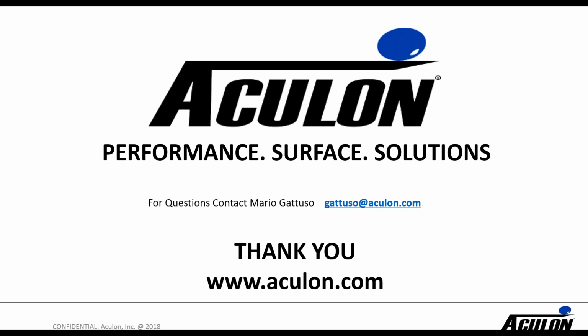I got a question here. A rule of thumb based on the IPC conformal coating handbook is 2 to 3 mils. How do you apply this material to achieve this requirement? So we're throwing out that handbook here. That's for old coatings. That's old knowledge. You do not need 2 to 3 mils to achieve the performance we're talking about. So we're not talking about applying multiple layers of coatings. The reason you need to do that is because those materials slump and don't coat the edges. So these are a different class of material, and I would not use those recommendations for applying the coating. You do not need that much material.